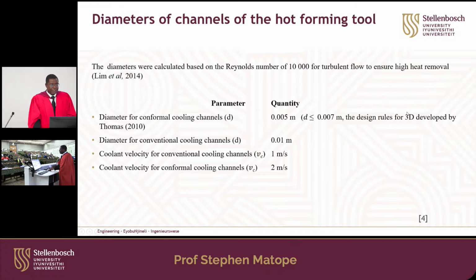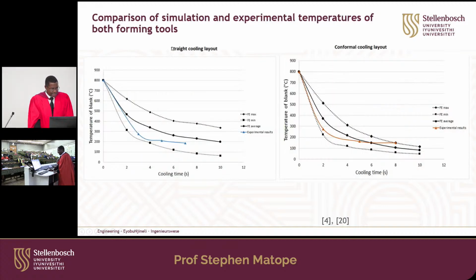Now, the diameters of the channels for the hot forming tool, where we have the one for conformal cooling, we are having it at 0.005 meters, but for the conventional, 0.01. Right, I think those are the values we used. After we did that, we then had to compare simulated results with our final experimentation. With that, we found that the experimental results were really better than our simulation.